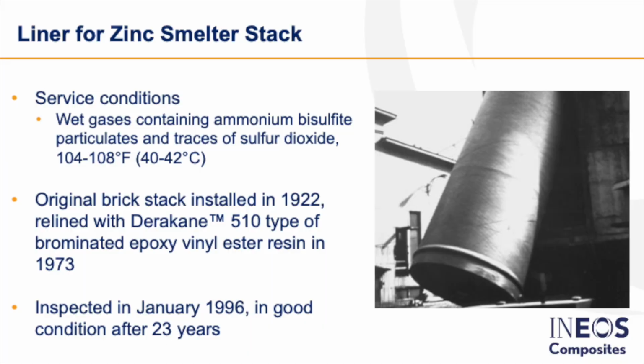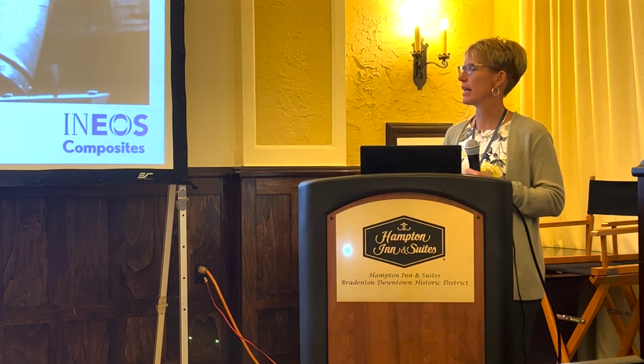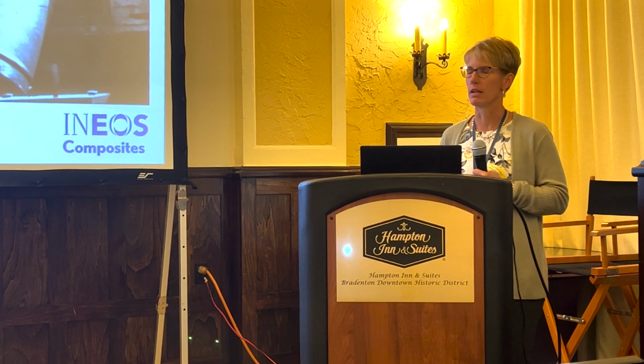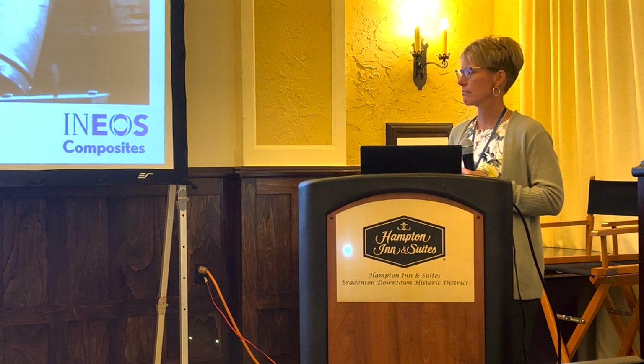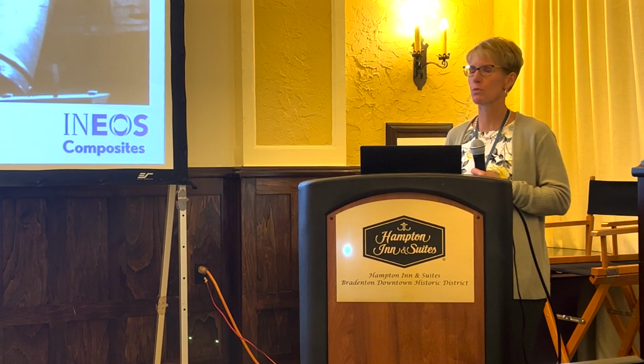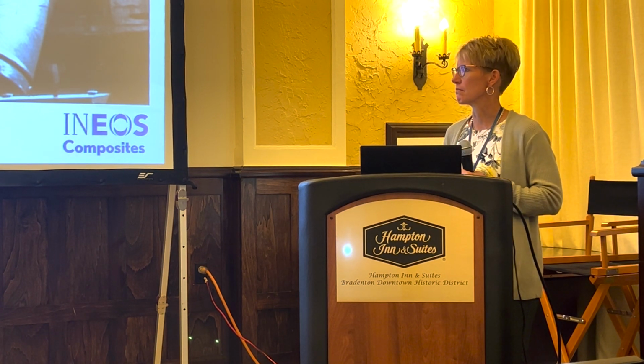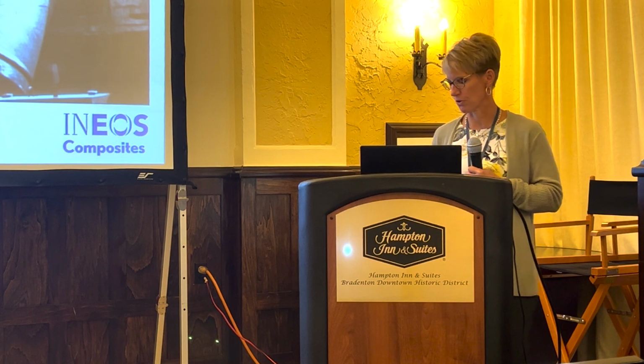This is a liner for a stack. The service conditions consisted of wet gases with ammonium bisulfite and some traces of sulfur dioxide. In this case, it was originally a brick stack that was installed in 1922, and then in 1973 they went in and actually lined it with the brominated vinyl ester resin. And as of 1996, when it was inspected, it was still in good condition after 23 years of service.